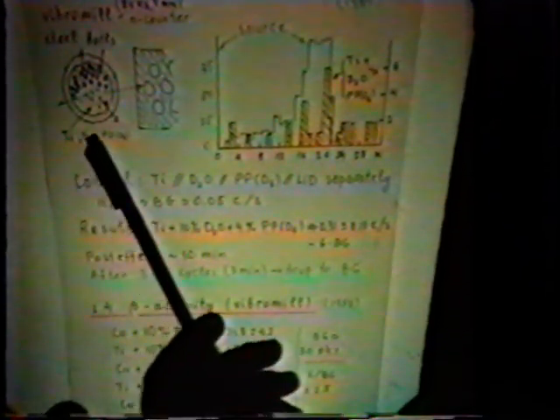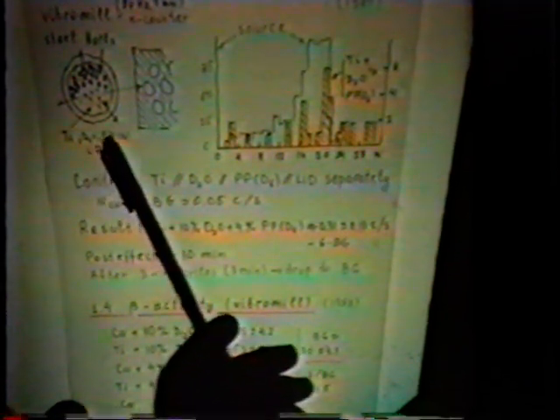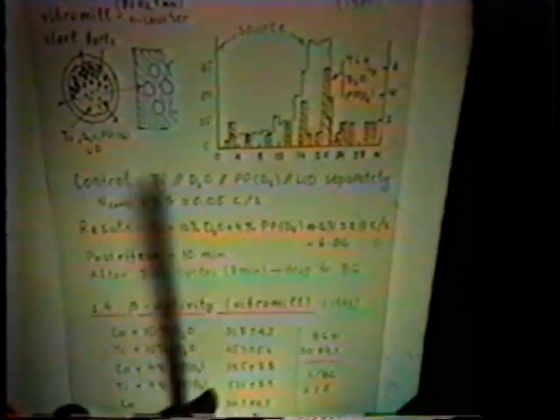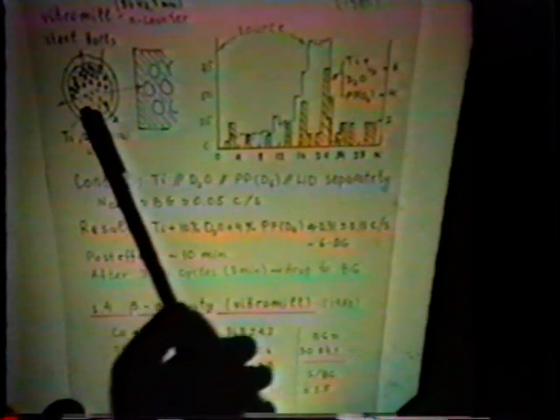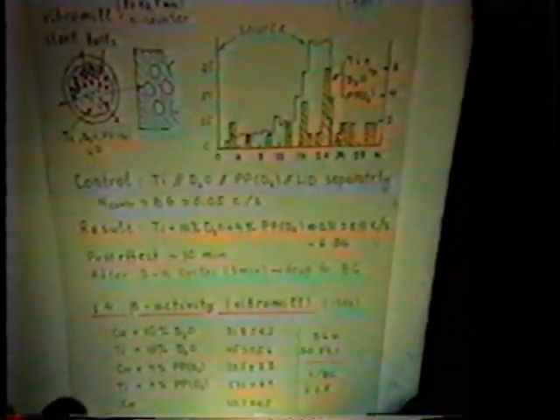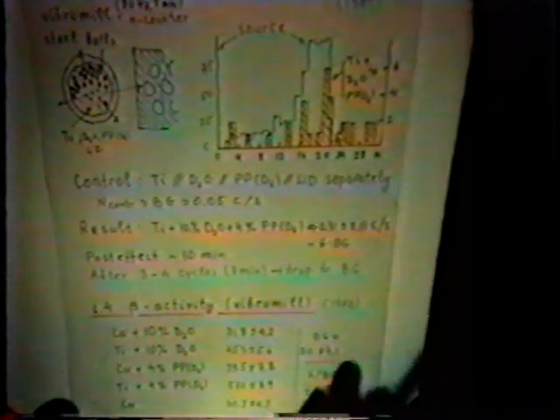Titanium chips, heavy water, lithium D crystals, and deuterated polypropylene were placed inside of a vibromill and tested, and the neutrons were measured. Here you can see the result of these measurements. For control of their data, they also measured neutron emission for all these materials separately.